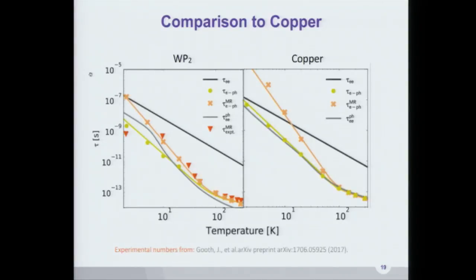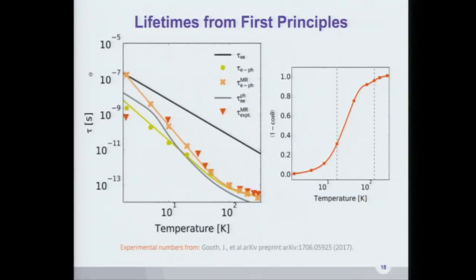So we said, OK, how do those same lifetimes show up in copper, presumably a better understood, less messy material? And again, for copper, we start to see contributions from different lifetimes, but we don't see that hydrodynamic signature. So it was kind of clear to us that the lifetimes we were identifying were grounded in reality. They're also grounded in reality because we're able to track the experimental outcome using that one particular set of lifetimes, and you don't see the other contributions from the lifetimes track that trend at all.